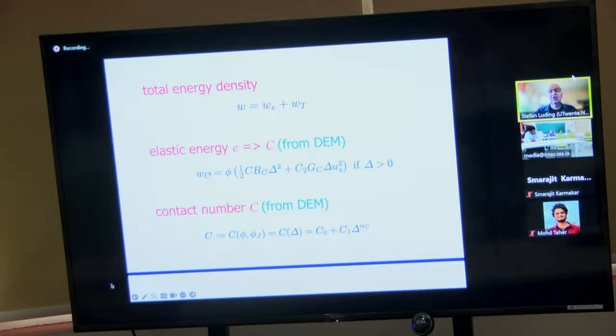And the elastic energy density is proportional to the density, to the volume fraction. There is the coordination number, there is an effective modulus, and there's the elastic strain squared. And there's the shear strain squared with the shear modulus in the second term. Okay, and since our granular matter has no long-range forces in the simplest case, the elastic strain has to be larger than 0, otherwise the elastic energy is not defined, so it's not there. So you have a transition from non-elastic. Above a certain density, at jamming, you will go to elastic, or you will activate the elastic energy. And maybe that's not all. There can be also thermal.